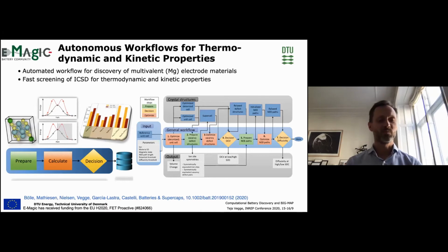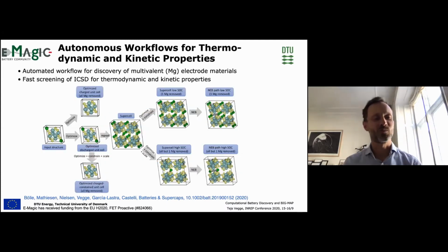And what Felix Böhle and Ivano Castelli did was that they prepared an automated workflow that searched the ICSD for structures with a certain magnesium coordination. We could then automatically assess what are the OCVs at high and low state of charge. If those are potentially interesting, we could continue to do a kinetic analysis. And what you see here is the workflow itself, but it's not good for presentation, so I'll move to a structural description of what Felix did.